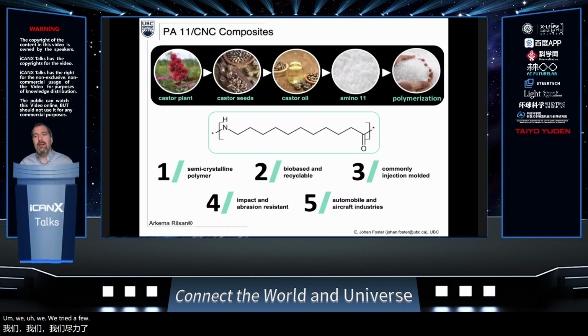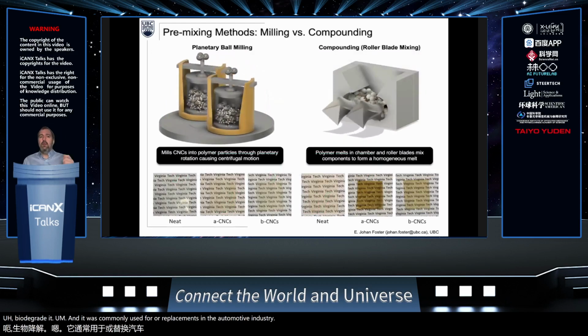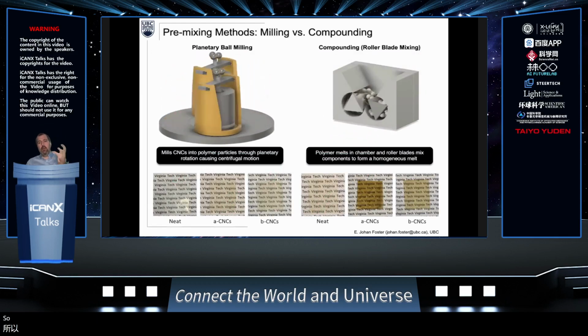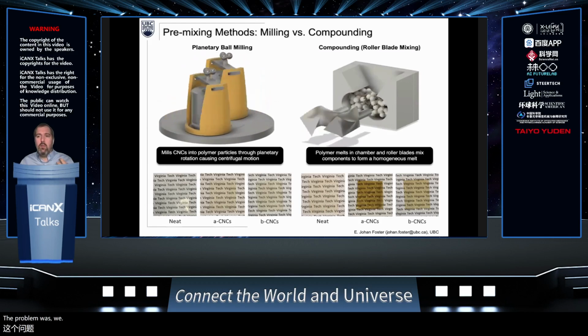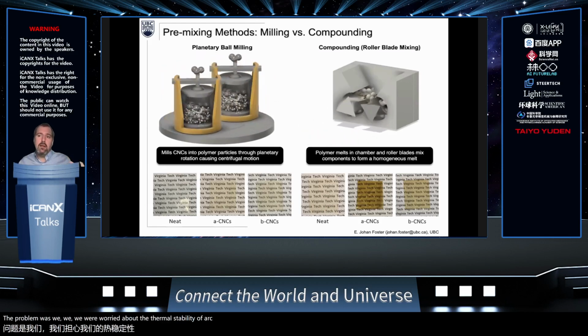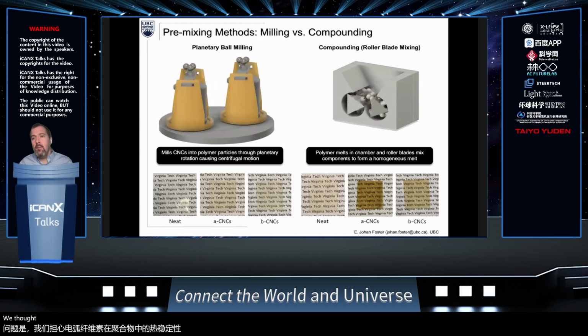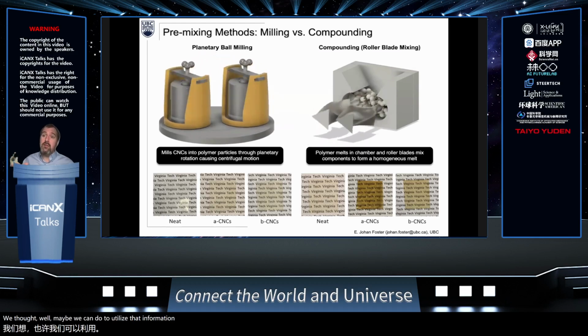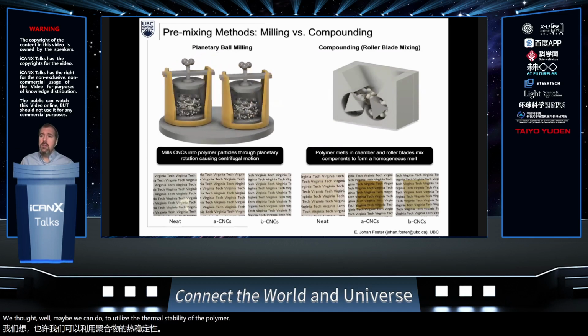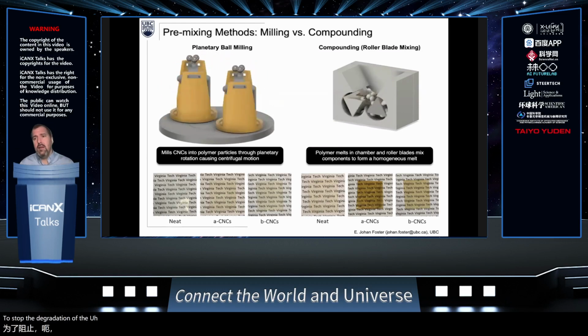We've tried a few other ones now. This was our first one, simply because it was bio-based, semi-crystalline. We could potentially recycle it and biodegrade it, and it was commonly used for replacements in the automotive industry. So the problem was we were worried about the thermal stability of our cellulose within our polymer. So we thought, well, maybe we can utilize the thermal stability of the polymer to stop the degradation of the cellulose nanocrystal.